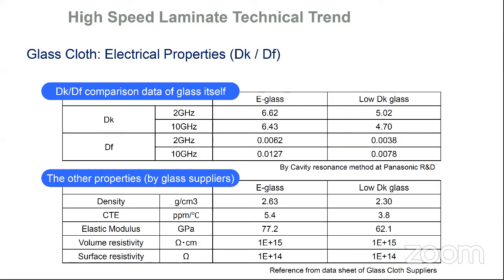But if you shift over and look at the net effect of specifying a low Dk fabric, you get a significant drop in Dk and Df. So by simply using and developing and improving, finding lower dielectric constant fabric, the resin system can stay mature for a longer period of time, where we can get our electrical performance enhancements, speed and loss through the use of the glass reinforcement, the lower Dk properties. The second part of this table simply compares some of the mechanical features of both the E-glass and the low Dk fabric. They're very similar in that particular example. Any questions there, Mark? No, I think I'm good. Thanks.